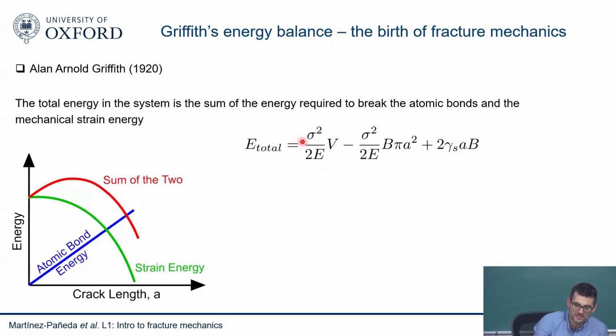And then if I plot this other term, you see that initially when a is equal to 0, it has its biggest value. But as a increases, this term starts becoming more significant. So I keep going down, down, down, and eventually it will be 0 when the crack has to span the whole thickness. So it looks something like this. The strain energy, as the crack is growing, because I have more unloaded part of material, goes down. And if I sum the two of them, I get the red curve here.